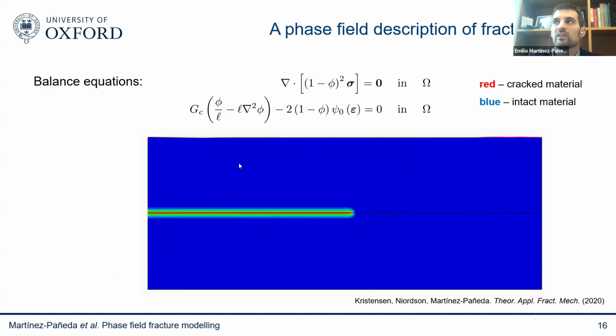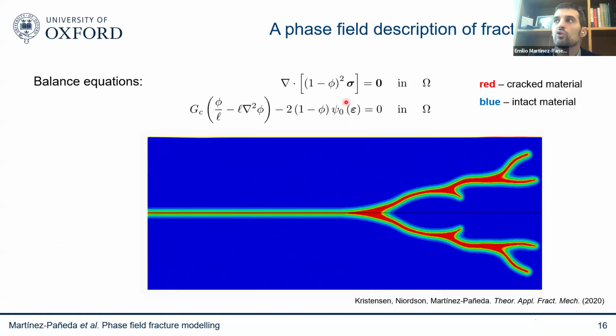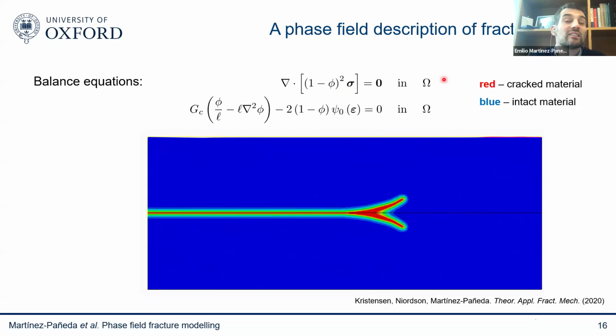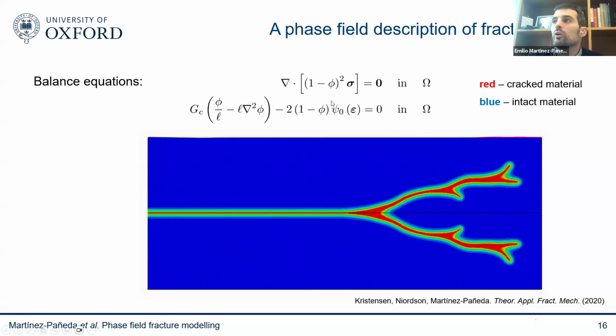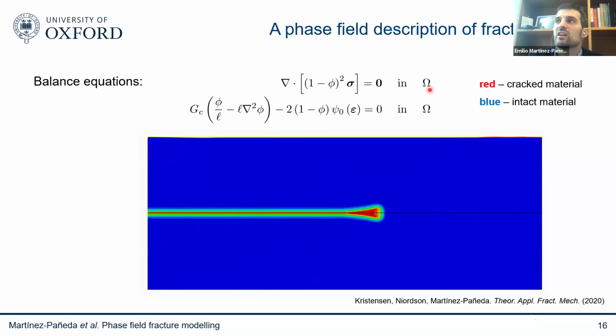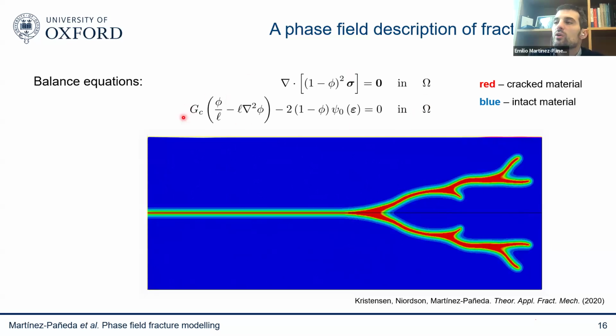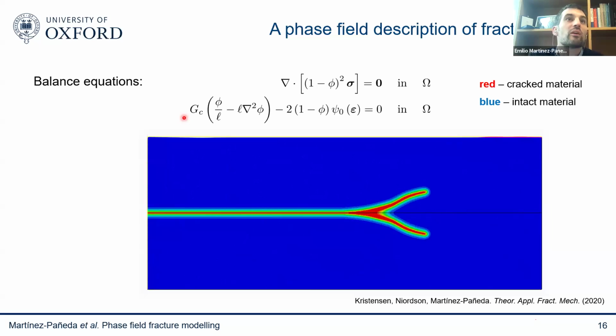And you can get a good overview of the method by just looking at the strong form of the balance equation. So you have the usual balance of linear momentum that you solve in any standard finite element simulation, where the phase field is degrading the load carrying capacity of your material. So whenever the phase field is equal to 1, you have a crack, no material to carry any load. And then the other situation that you have is a differential equation for the evolution of the phase field, which is effectively a competition between the strain energy density that increases with mechanical strains, the energy stored in the material, and the material toughness, GC, which is something that we can measure through a fracture toughness experiment. And just by solving this differential equation, we're able to capture fracture problems of arbitrary complexity.